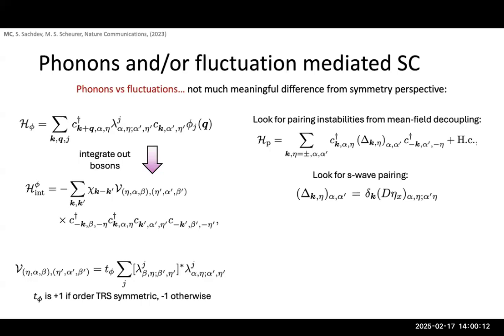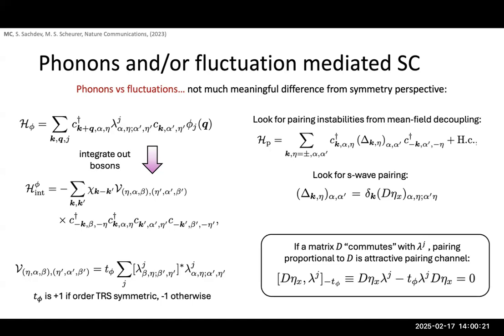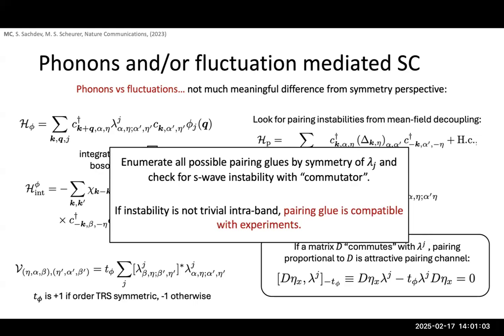So if you write the pairing in this form, where you just assume it's momentum independent, then you can write down a criterion of how this pairing must commute with these matrix elements lambda for this pairing to experience an attractive interaction. So if this criterion is satisfied for an S-wave pairing, then since an S-wave pairing and a pairing with a sign change both have an attractive interaction, we expect, given everything else to be equal, the S-wave pairing will be favored. And so what we can do now is just, trying to be as agnostic as possible, start writing down what are the possible lambdas classified by symmetry that we can consider, and what are the leading instabilities for each lambda if they have this S-wave type instability. And then if the instability is not this trivial intraband S-wave state, we can say that the pairing glue is at least not incompatible with what's been seen so far in experiments.